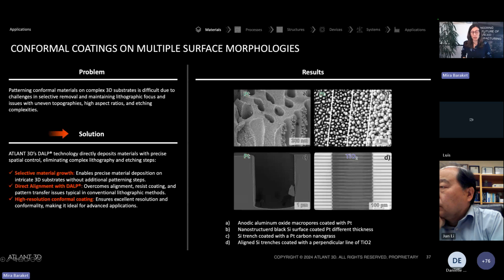So what we are enabling here is the conformality of the deposition of the coatings, but also selectively depositing on the surface. The examples I am showing you here are for deposition on different types of corrugated materials. On the top left, we are showing the anodic aluminum oxide that is coated with platinum. And on the right here is another structure, which is a black silicon surface that's coated with platinum. Also in trenches, this is also something that is usually difficult to do selective deposition on with the normal techniques. And with our technique, you are able to deposit conformally, but also directly on trenches, as can be shown in the two bottom pictures.